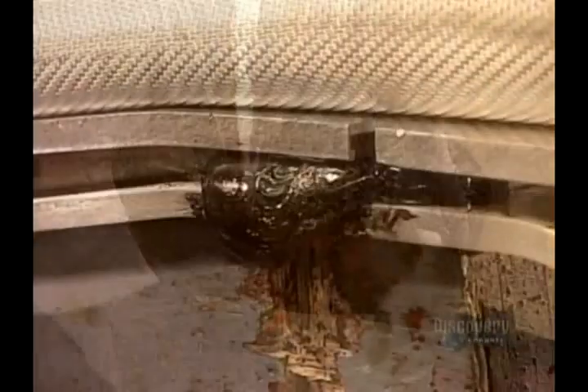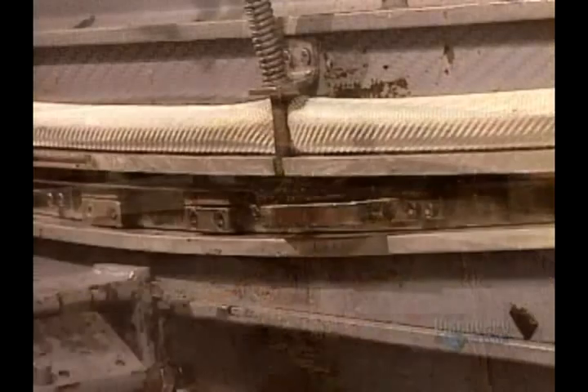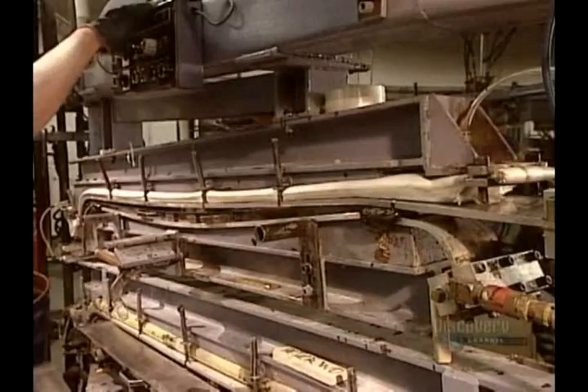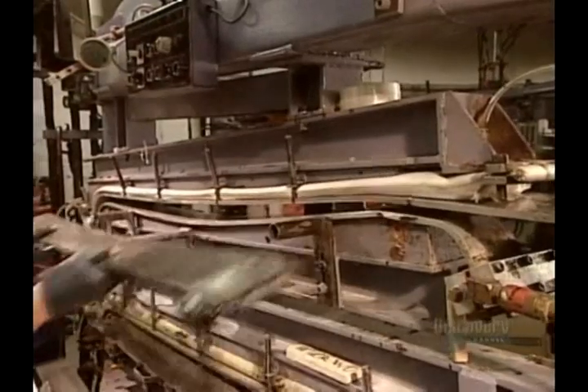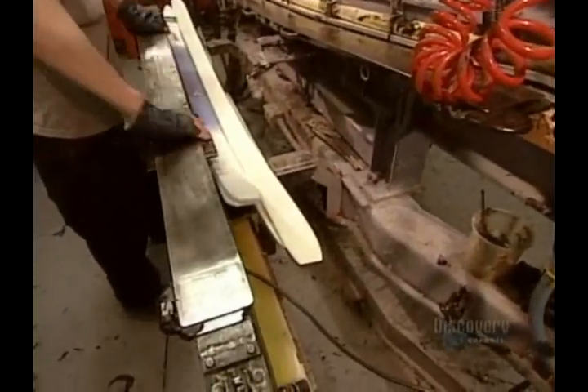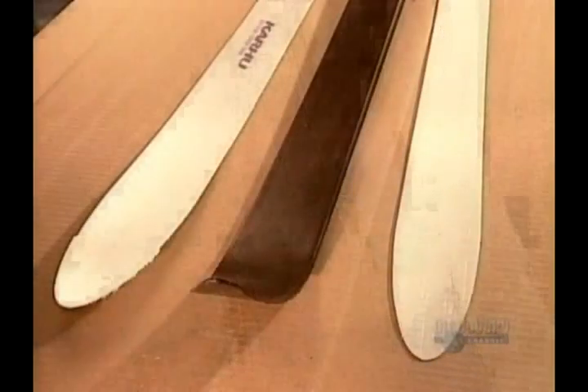This demonstration shows what happens. First, the polyurethane inflates. Then, it hardens. After 8 minutes, it's hardened enough to come out of the mold. They let the ski cure for up to 8 hours, at which point it's strong enough to support the weight of a skier. So now these 3 components, the top layer, the polyurethane middle, and the gliding surface, are one.